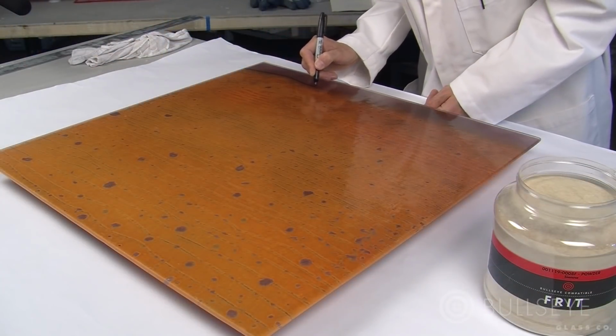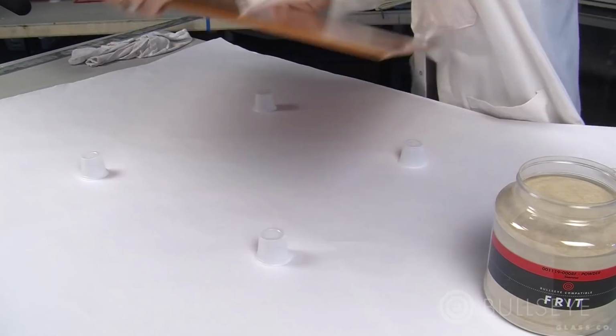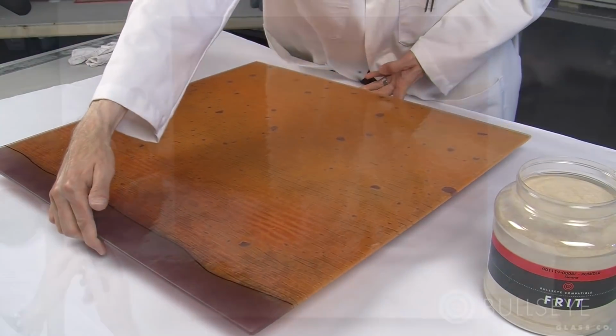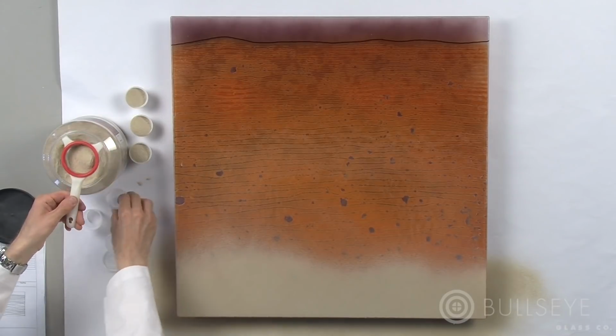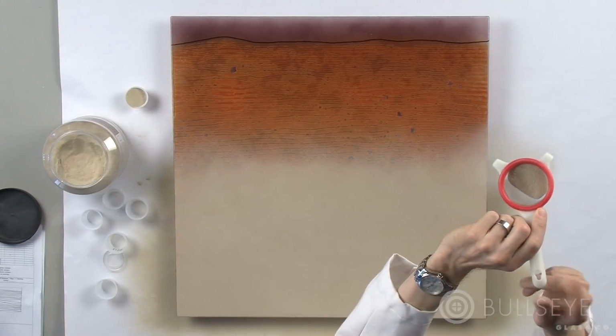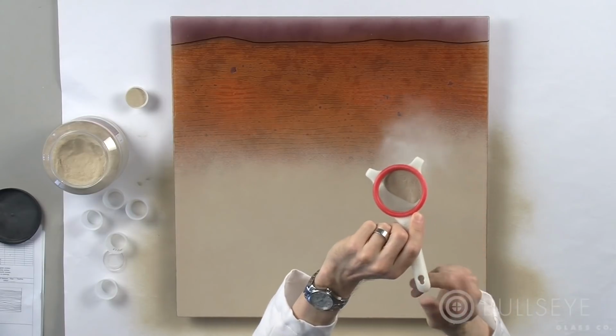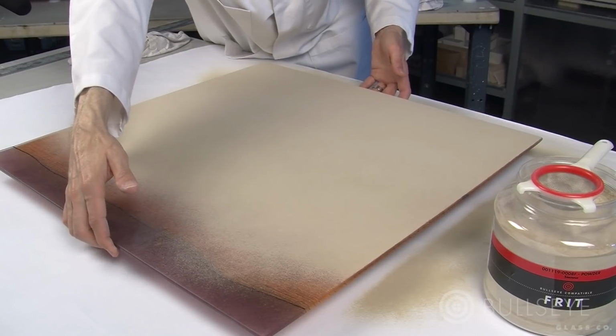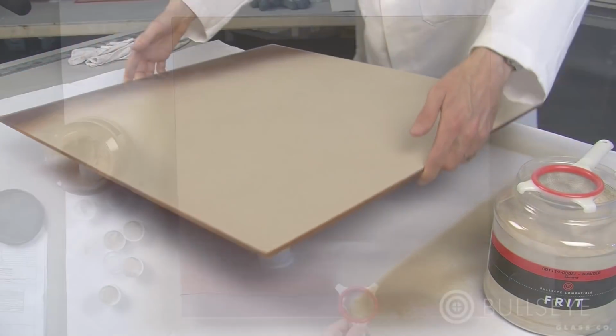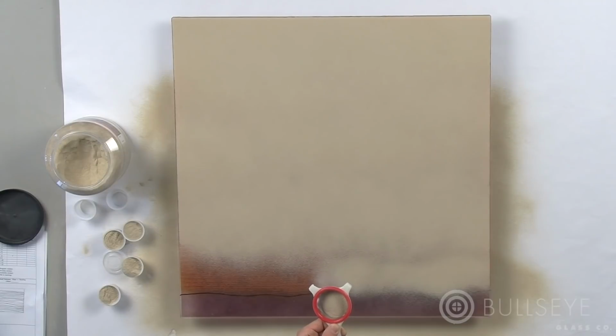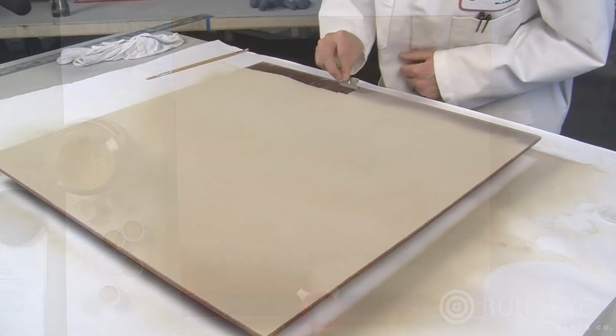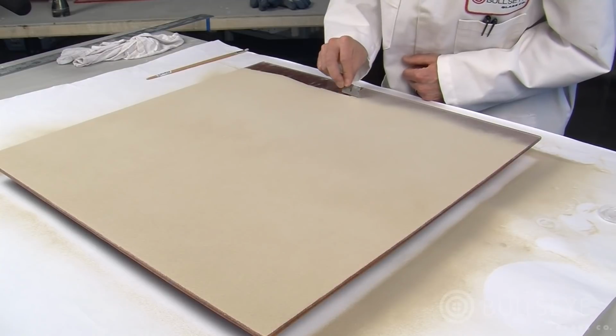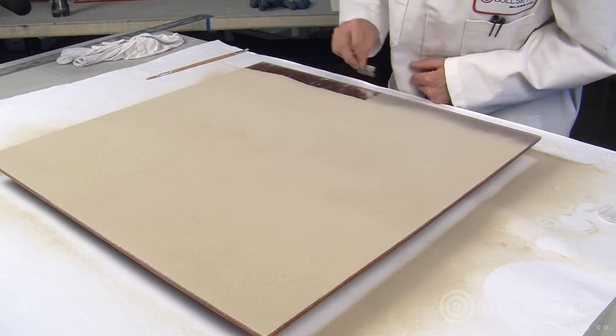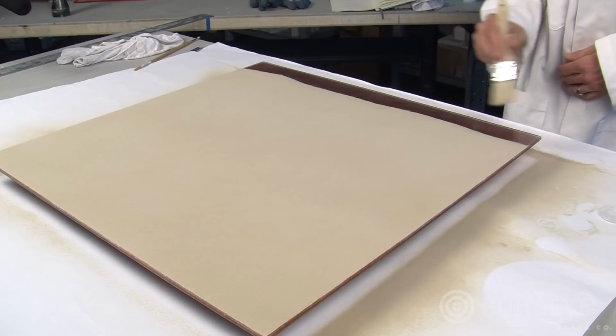And now I'm starting on the second piece again, working on the other side. And I've drawn a line on it, and I put 11 cups of 1119-08 sienna powder onto the piece with the sifter. And again, I find myself not able to quite reach to the other side. So I turn the piece around. And here I'm using a razor blade to clean up the top portion of that composition to get a nice crisp line up there, and then a brush to clean up any overspill.